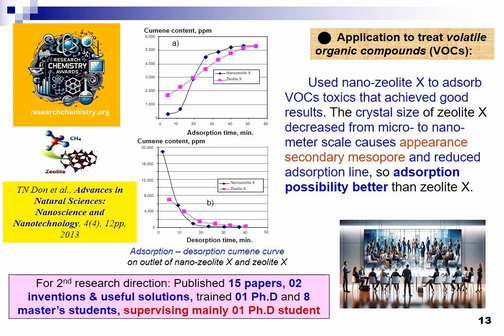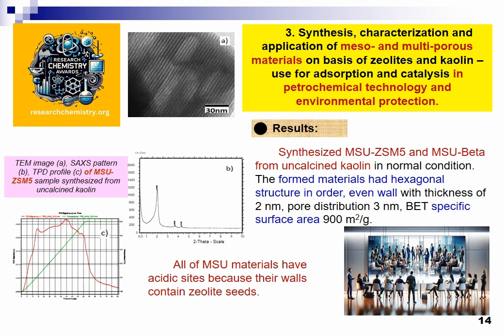We have used nanozeolite to adsorb VOCs toxics and achieved good results. The crystal size of zeolite is decreased from micro to nanometer scale, which causes the appearance of secondary mesopores and reduces diffusion limitation. So adsorption capability is better than that of zeolite.